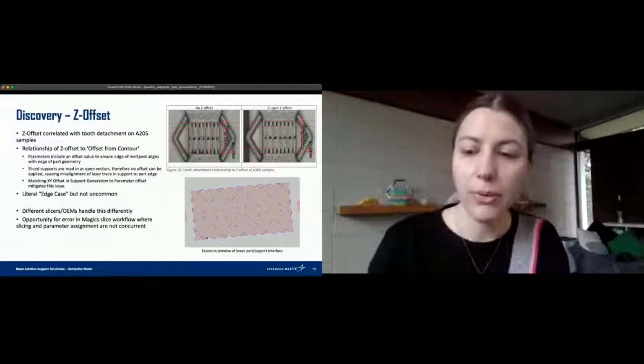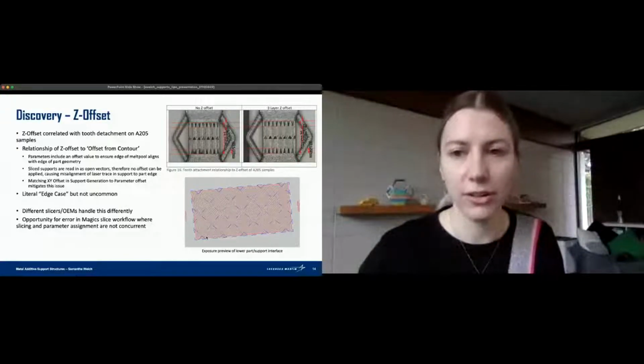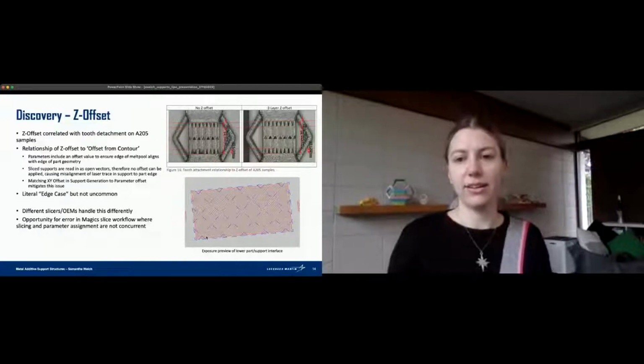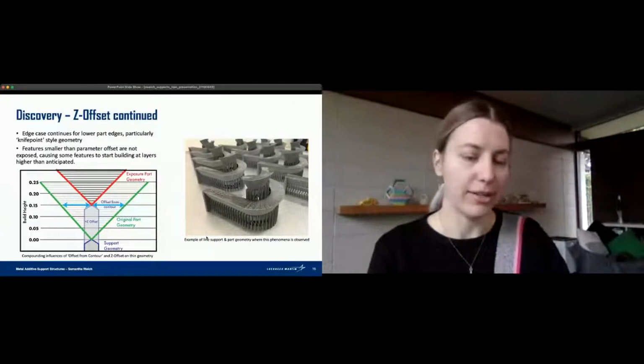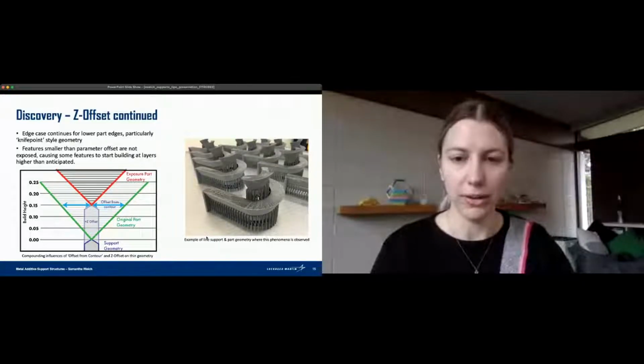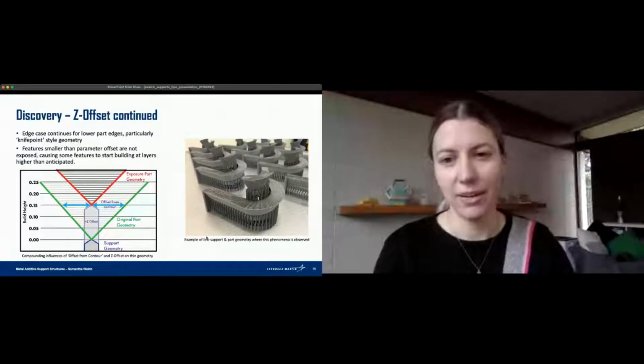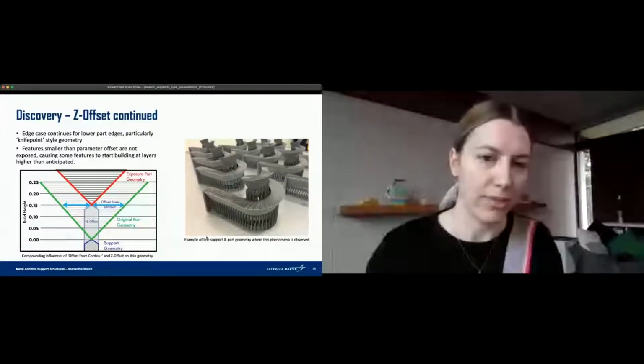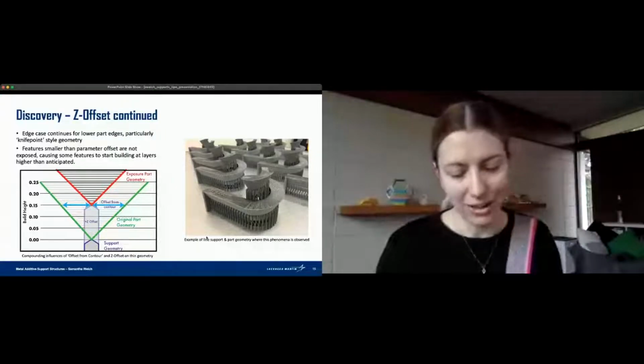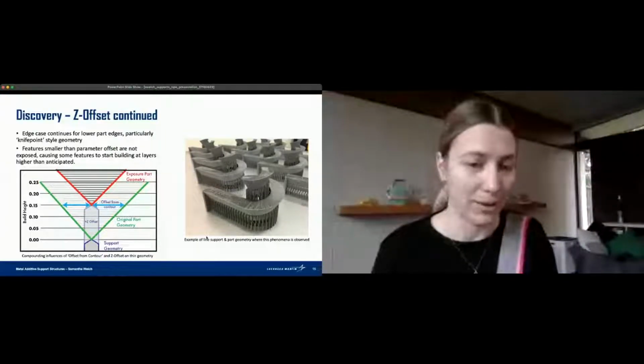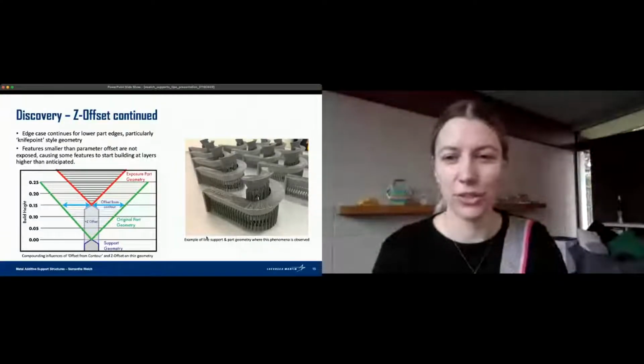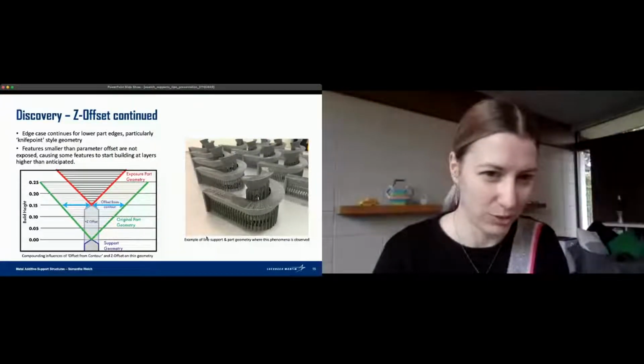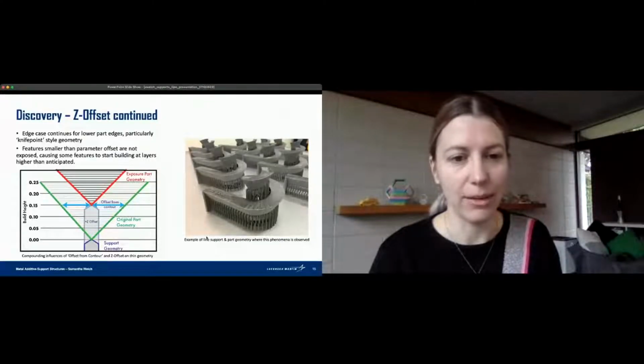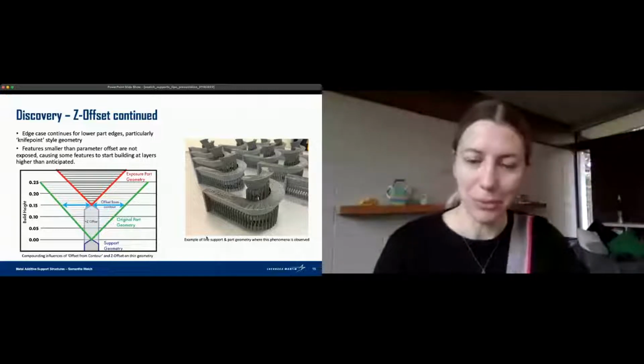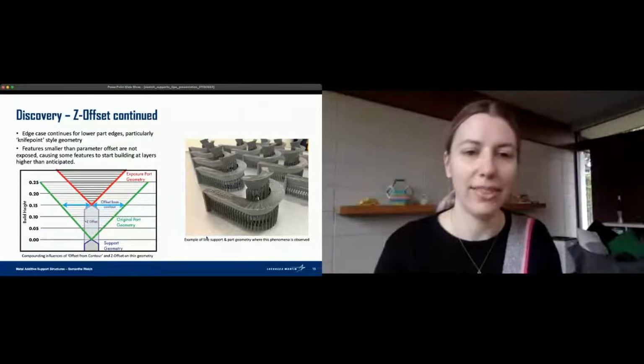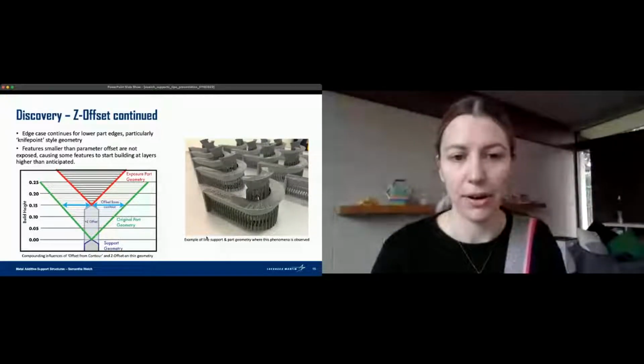It gets really quite interesting when we get to it over multiple layers. So one of the edge cases we were seeing is that, as people often do, we had parts that we wanted to start on an edge and then grow into a part. And so we'd have a single line of supports attaching it, but we were seeing a lot of weird effects and some detachment there. And this is because that offset, as our part is offset within the melt pool bounds, makes it so those first few layers have no exposure attached to them, because it's offset smaller than a value that the melt pool would project. So this actually then pushes my part up a layer. And depending on what that melt pool offset is, that can push up your part multiple layers.